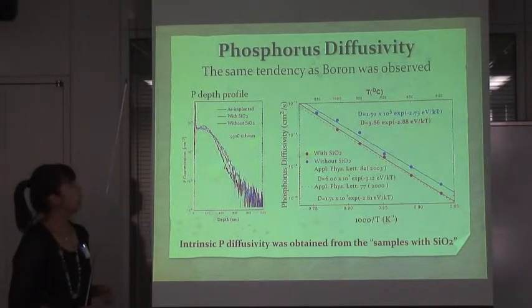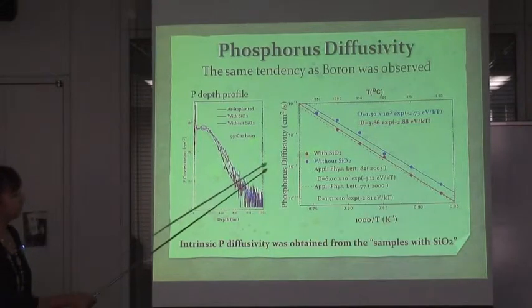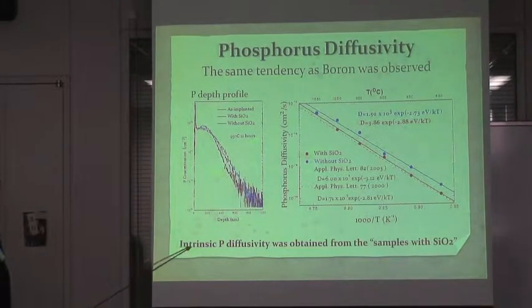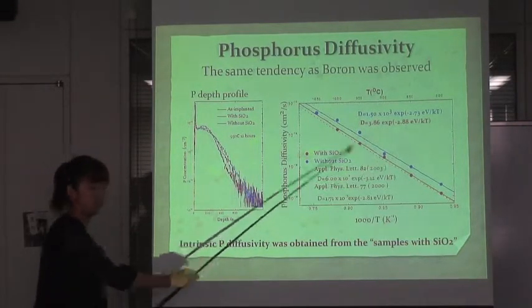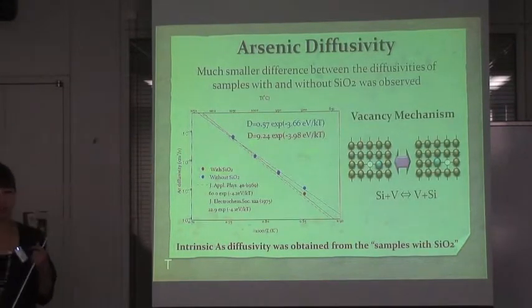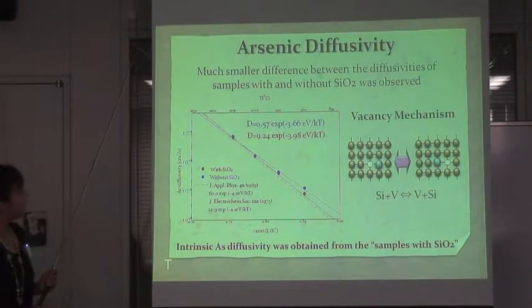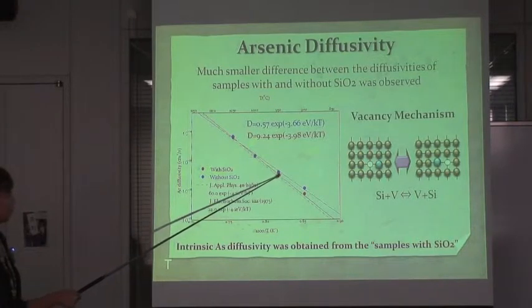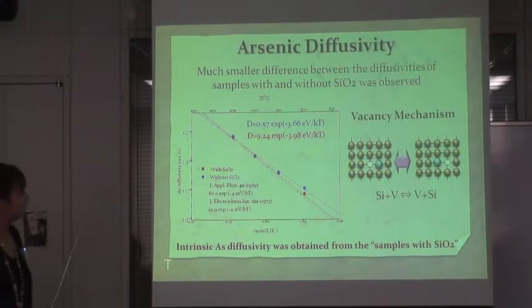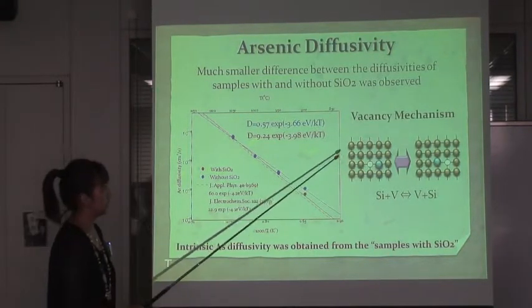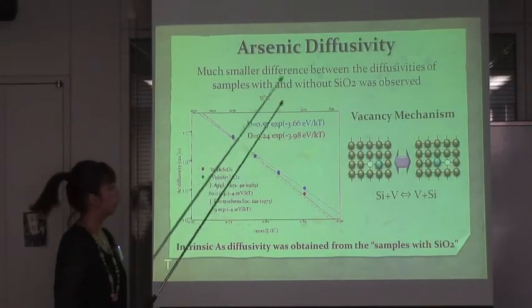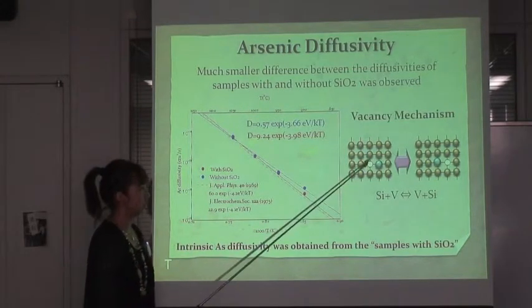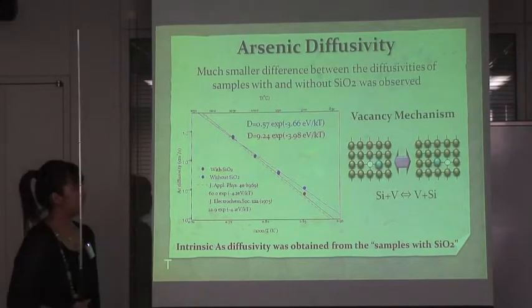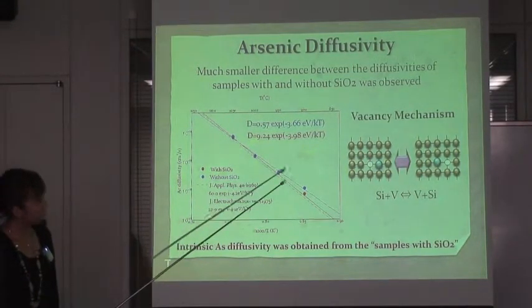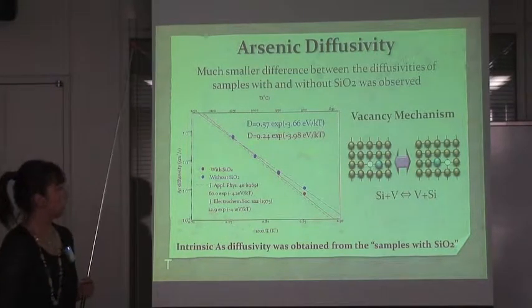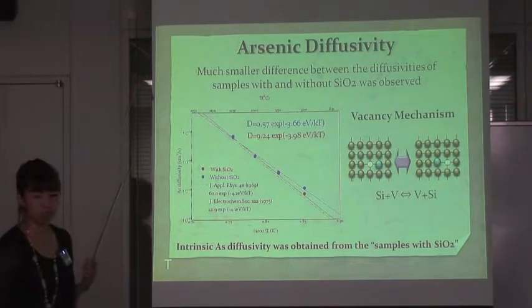For phosphorus diffusion, the same tendency as boron was observed, like this. So we obtained intrinsic phosphorus diffusivities from the samples with silicon dioxide. For arsenic diffusion also, we obtained the same tendency as boron and phosphorus, but a much smaller difference between the diffusivities of samples with and without silicon dioxide was observed. This is because arsenic diffusion in silicon is caused not only by silicon interstitials, but also by vacancies, and then oxidation enhanced diffusion is less affected compared to boron and phosphorus.